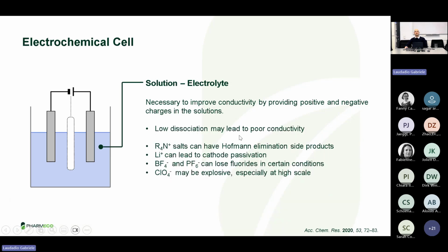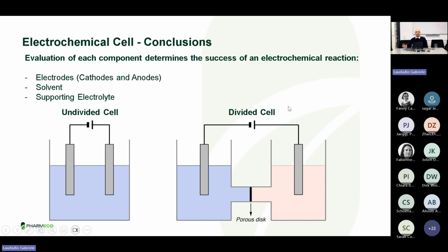In particular, we have to take care of the dissociation of these ions. It's important that these ions get solubilized, so surrounded by solvent while they are in the solution, so that the ion pair is not sticking together, in order to maximize our electrical conductivity. Okay, so to conclude the evaluation of the cells, the choices that we can make in terms of the design of the reaction vessel for synthetic organic electrochemistry rely mainly on the selection of the appropriate electrodes, cathodes and anodes, the selection of the appropriate solvent, and the use of a supporting electrolyte. Knowing this, now we can explore the physical fundamentals of electrochemistry.